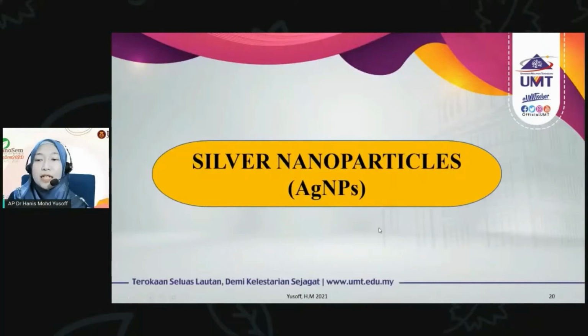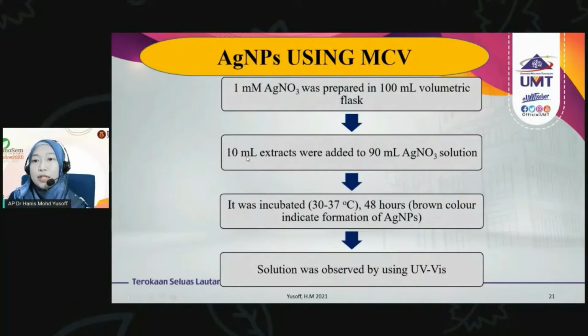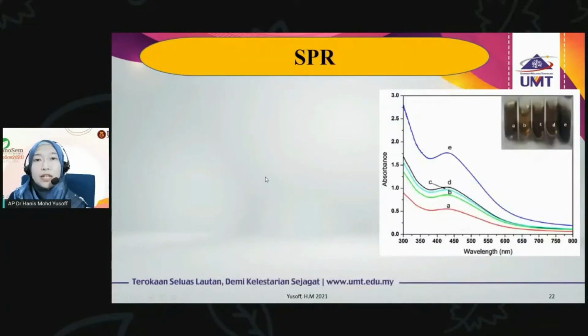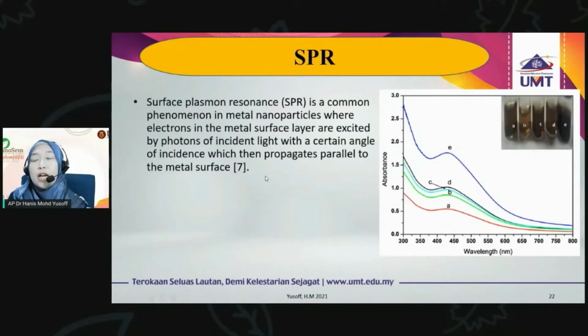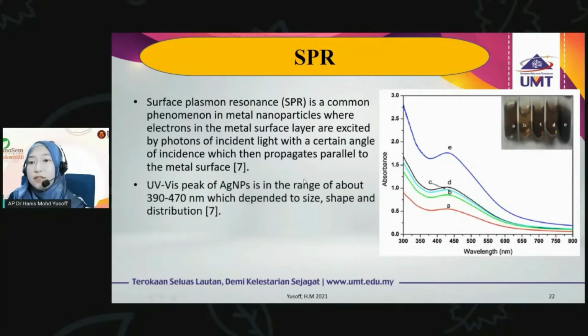Okay, move on to the first metal nanoparticle, which is silver nanoparticles. This is the method. We use 10 ml of the extract mixed with the silver nitrate and then incubated. As you know, it is very common for nanomaterials to have this SPR, or surface plasmon resonance, property, where the metal vibrates when light is excited, and at a certain angle it will propagate parallel to the metal surface. So we can monitor the silver nanoparticles by these SPR properties.